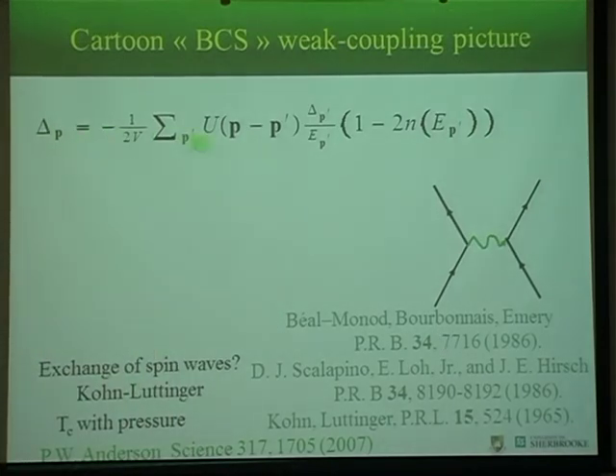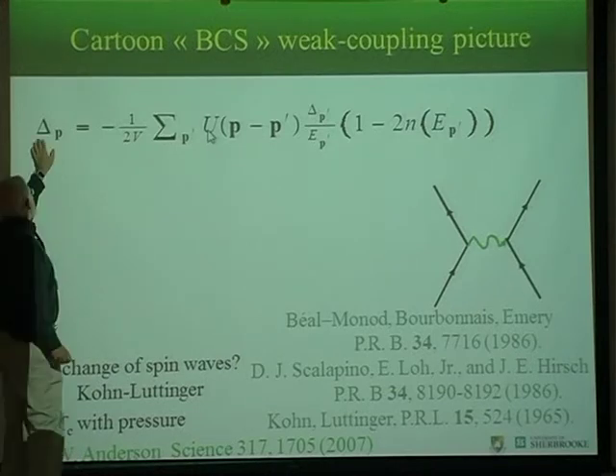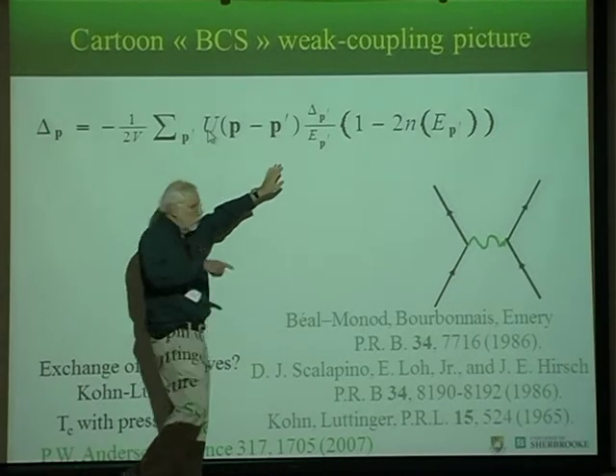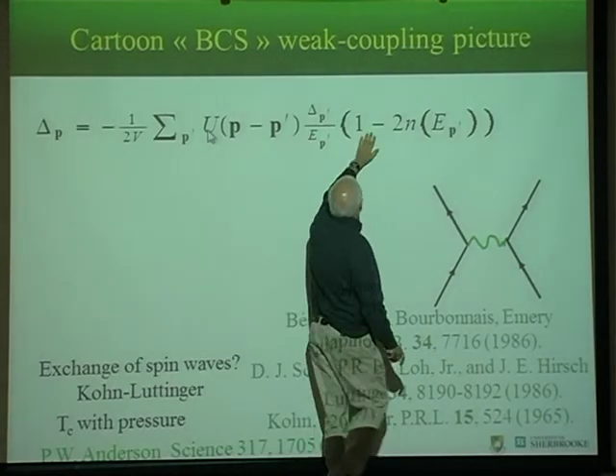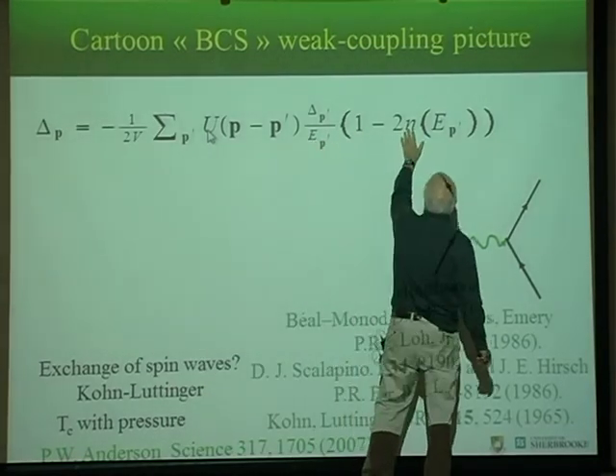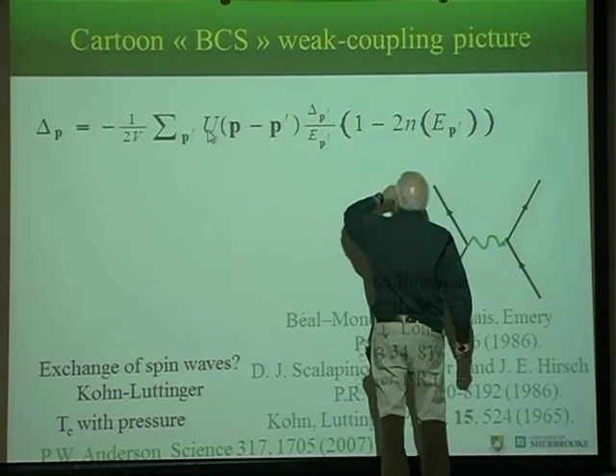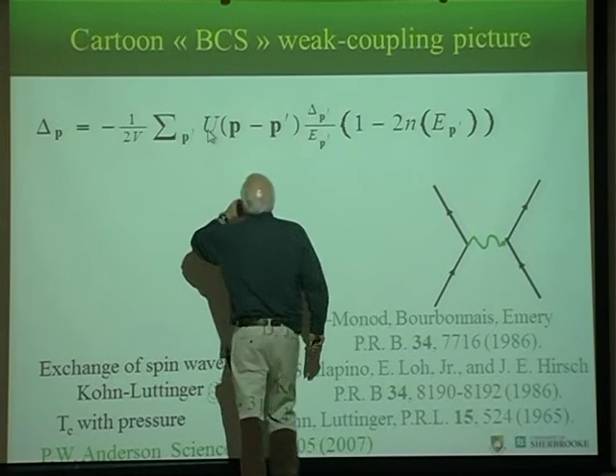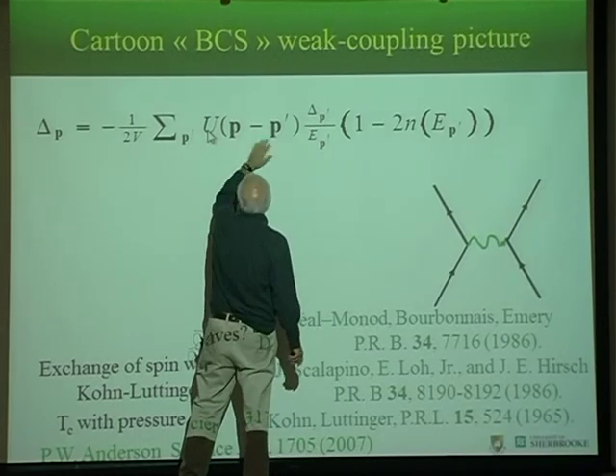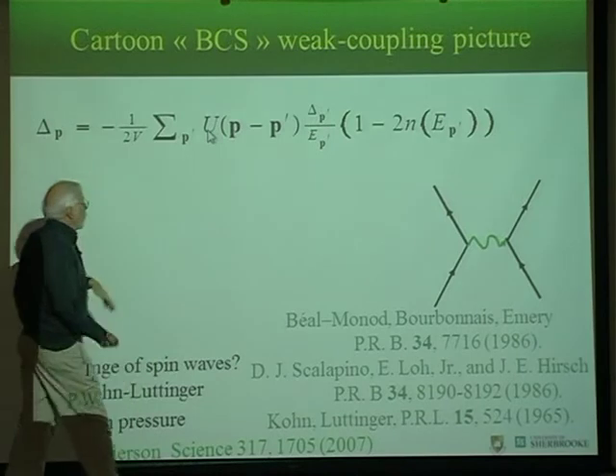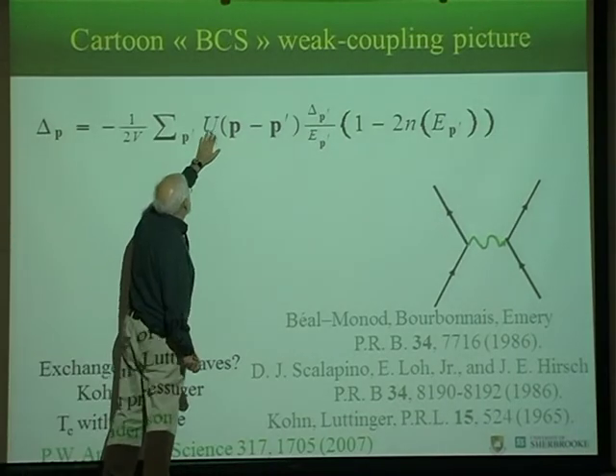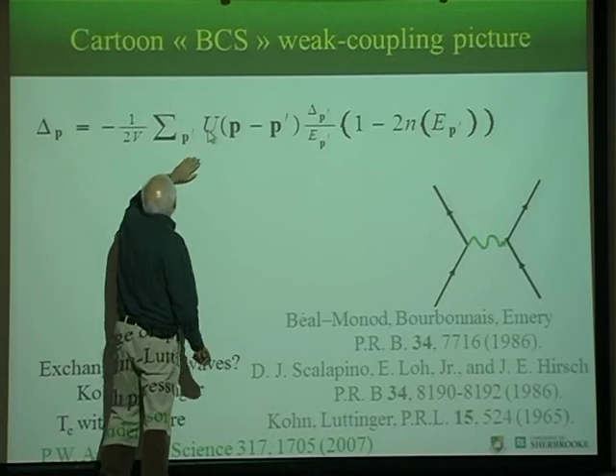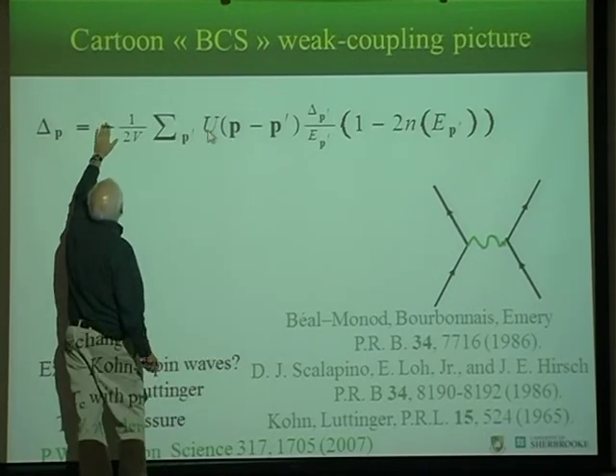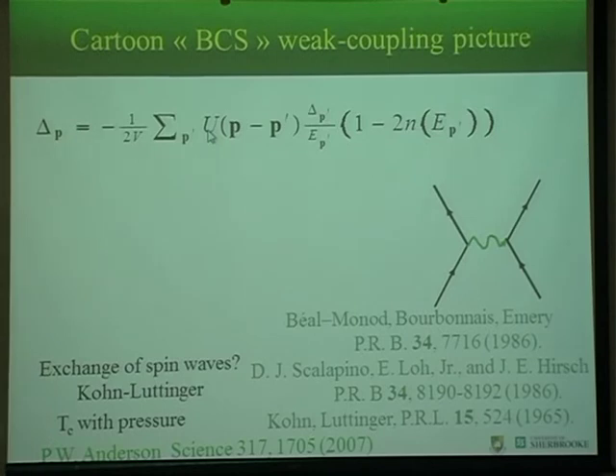And if you look at the BCS gap equation, one way to understand what's going on is like this. Let's talk about the usual case first. The usual case is that the gap is independent of direction, so it's S wave. Now this factor here is positive because E is a positive number, so the Fermi function is less than 1/2. Now this is the effective potential that could come from phonons. So in the case of S wave, if this U is attractive, then you have a minus sign, you get rid of this minus sign, and there's a self-consistent solution.